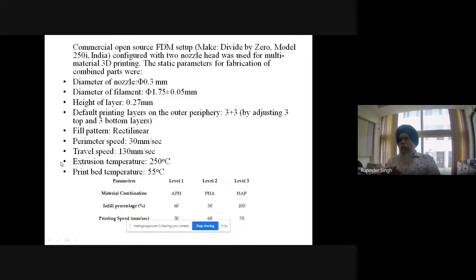You can see there are around 15 plus parameters that I can play with in my software, right? Some of the parameters we kept fixed, and some we tried to vary. In this case we varied the material combination, the infill percentage, and the printing speed. In the material combination, APH means the lowest layer of ABS, the middle layer of PLA, and the top layer of HIPS, right? So we tried to see how a multi-material printed substrate is going to behave.